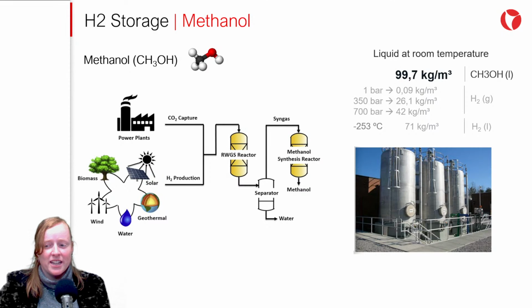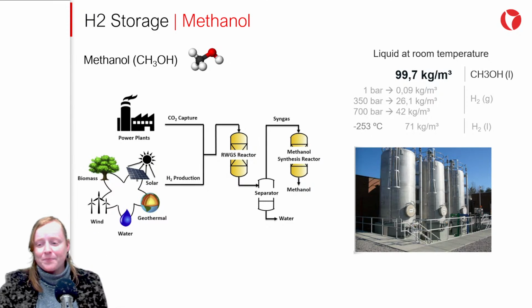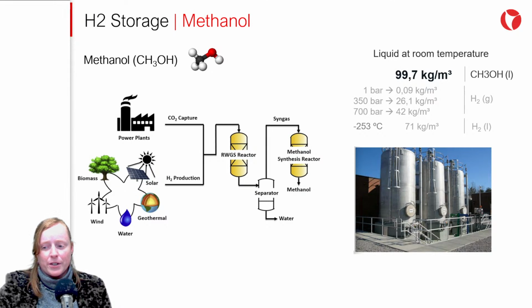Guidelines for the design, fabrication, erection, repair, and protection of above-ground methanol storage tanks are essentially the same as those for liquid transportation fuels, with some specific considerations. An important consideration is the flammability range, which is much greater than that of gasoline. Methanol vapor presents a greater risk of igniting within the void space of the tank. Another consideration is corrosion. Galvanic and dissimilar metal corrosion in methanol service can be high if incompatible materials are brought into electrical contact with each other. Cathodic protection and inspection of internal components are vitally important to avoid corrosion failures.